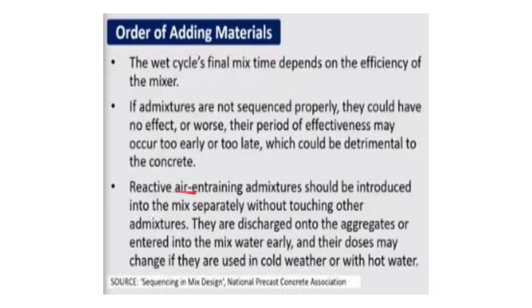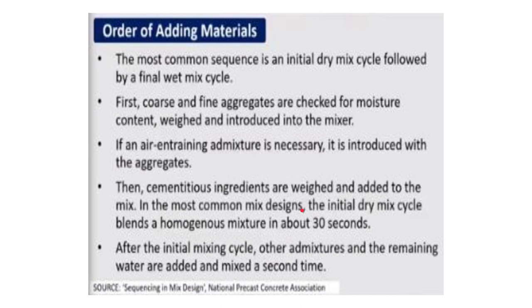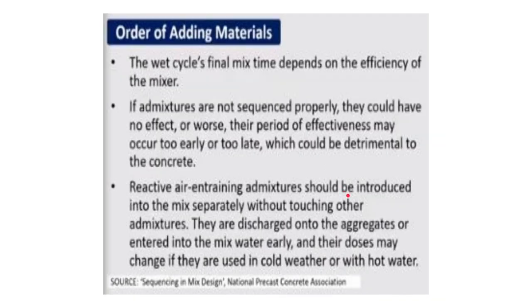Basically, the reactive air entraining admixture should be introduced into the mix separately, without touching other admixtures. They are discharged onto the aggregates, or entered into the mixed water early, and their doses may change if they are used in cold weather or hot water. So these are some of the criteria which need to be checked and kept in mind while preparing, so that the actual desired result is obtained in a practical sense.